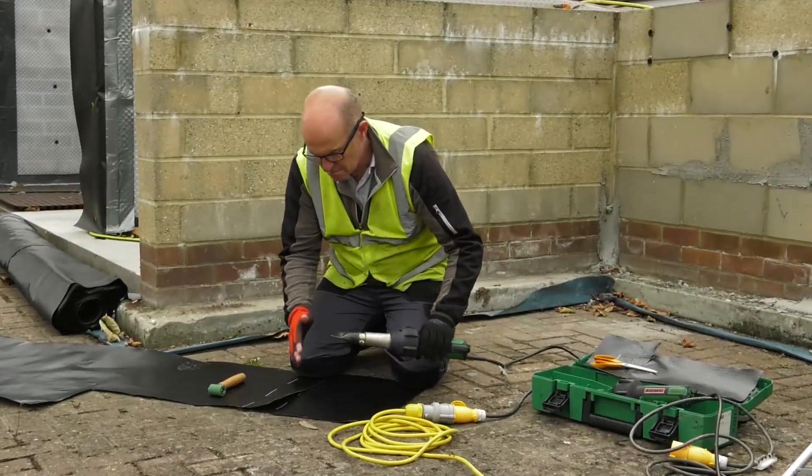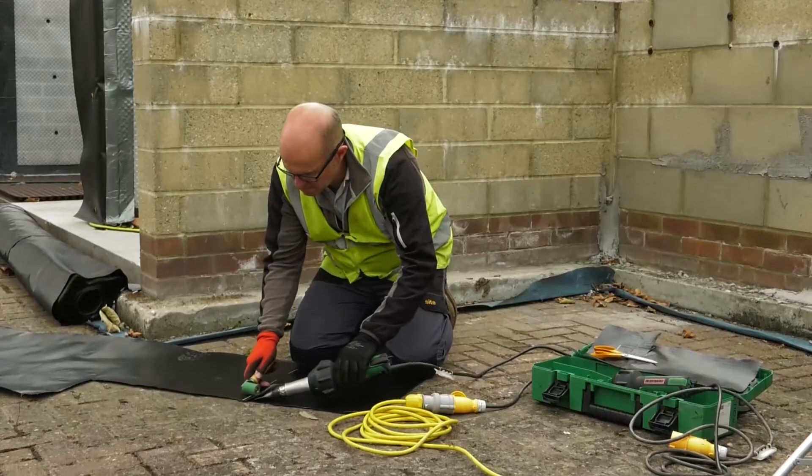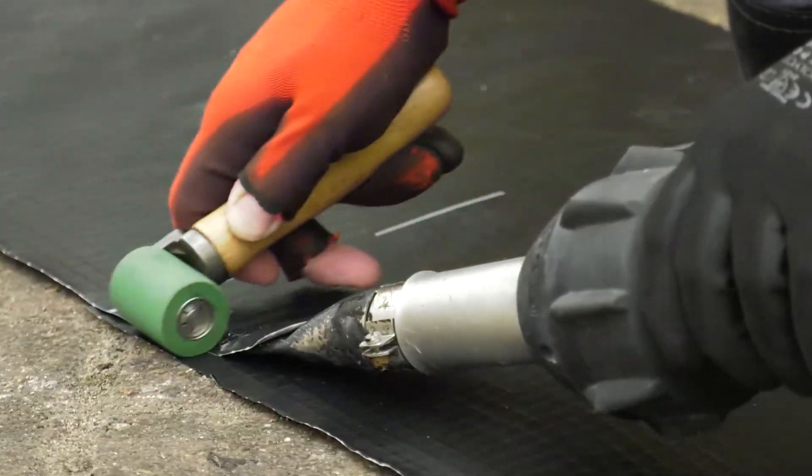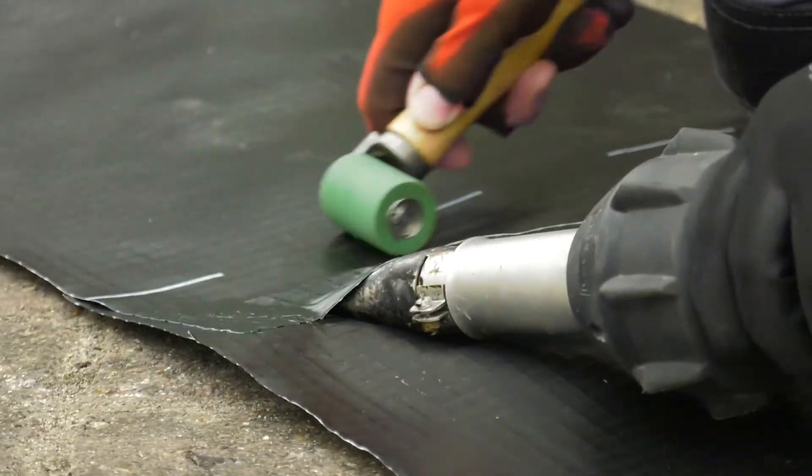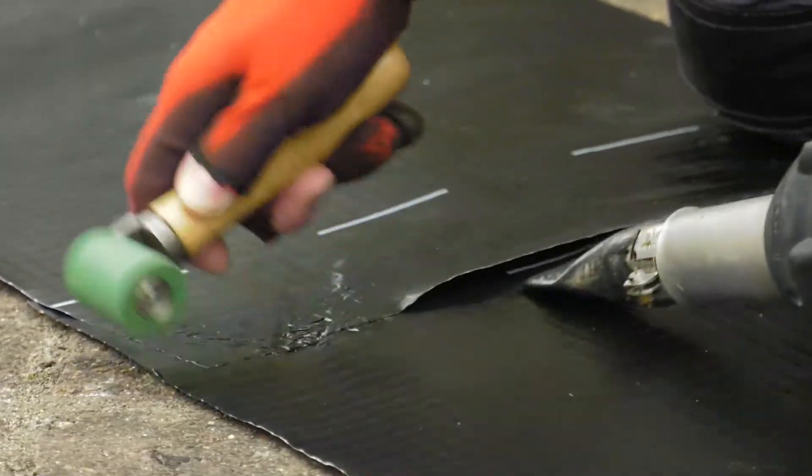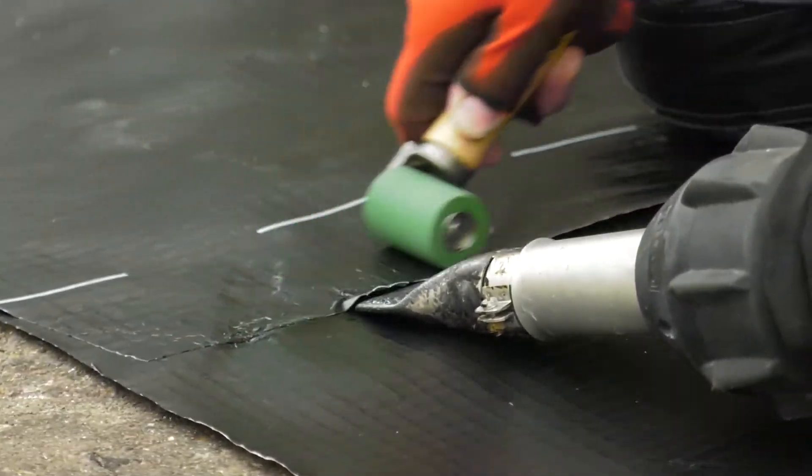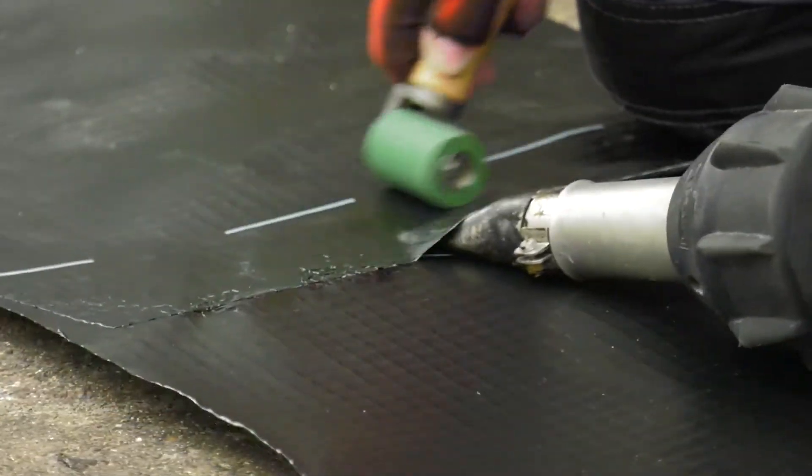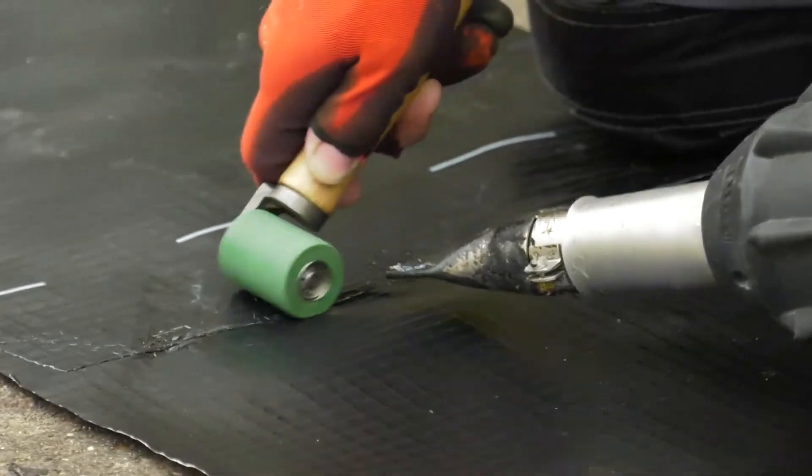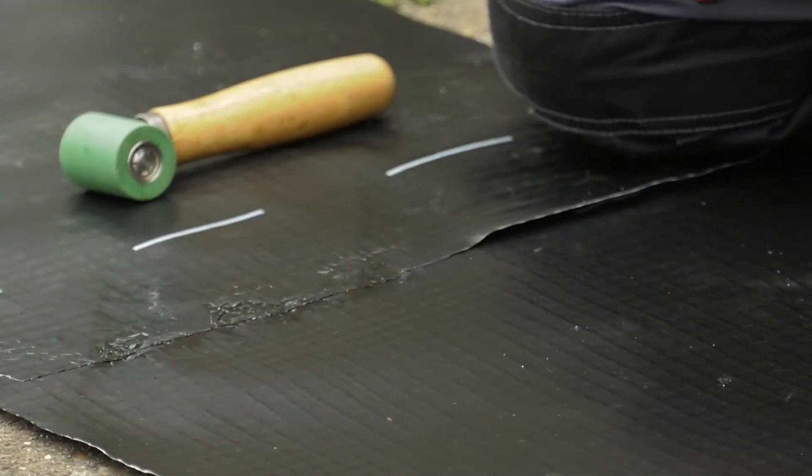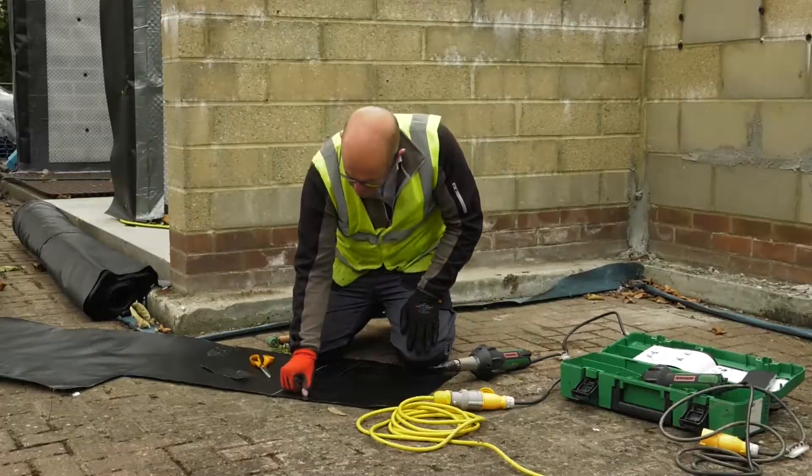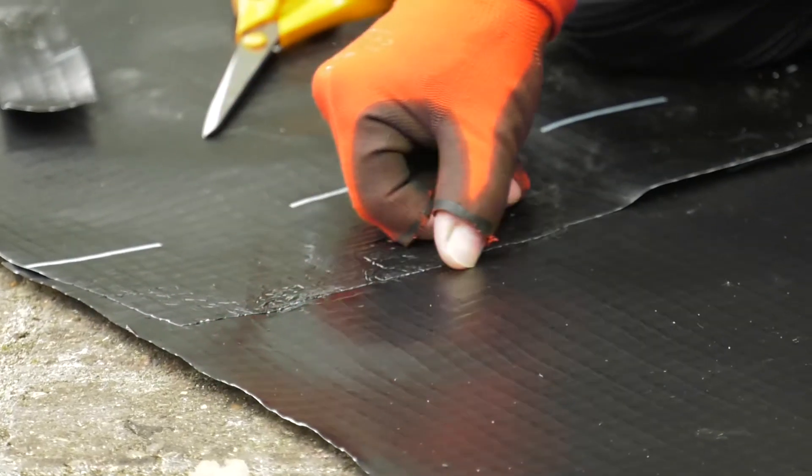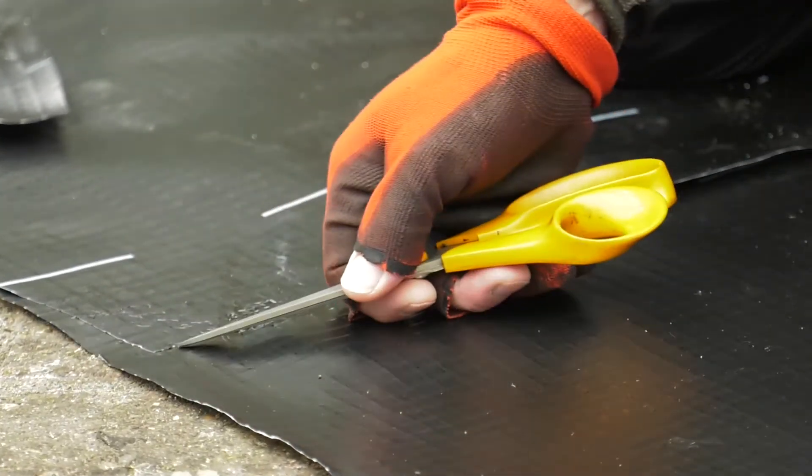With the heat gun fully warmed to the required temperature, we can now apply the nozzle between the two sheets and use the roller to apply pressure to fuse the two membranes. This is normally conducted as a test seam at the beginning of the day, just to confirm that the welding is compliant. We can also use the scissors, the pick test probe, or use the mechanical stress point test.